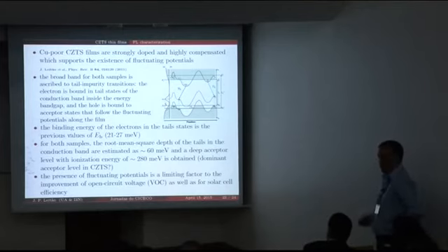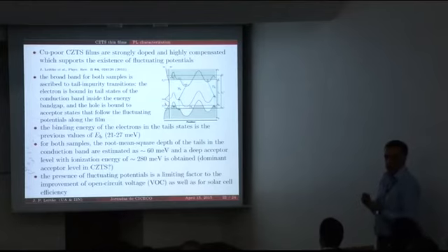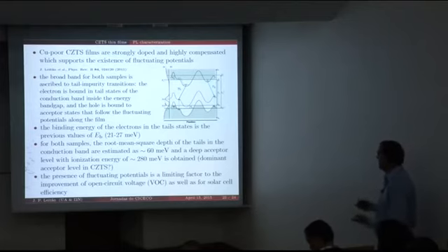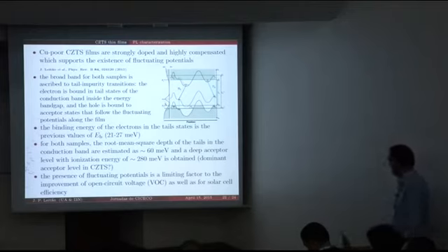This is quite different from what we observe in lightly doped semiconductors. So we have heavily doped and compensated semiconductors, and the radiative transitions that we are observing involve the binding of an electron in agglomerates of donors with holes connected to acceptor levels that follow basically the fluctuations in the bands. The presence of fluctuation potentials is one of the limiting factors for the solar cell efficiency.